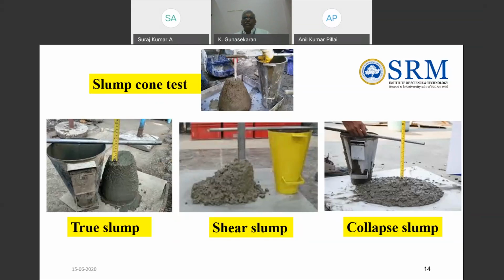If this type of slump happens, it indicates a lack of cohesion in the concrete mix. This shear slump may occur in the case of a very harsh mix. It may undergo some segregation and bleeding, and therefore it is undesirable, especially from the durability point of view. The third one is the collapse slump. It indicates that the concrete mix is too wet, and the mix is regarded as a harsh and lean mix. So it is completely collapsed.